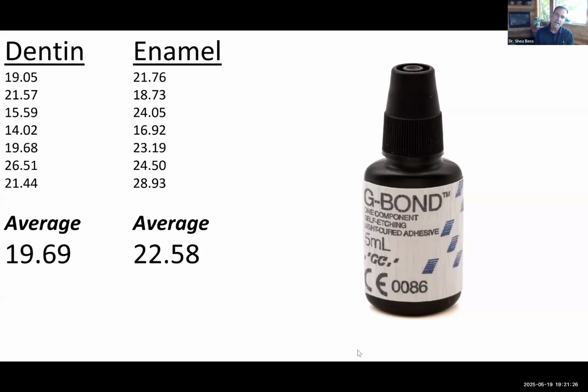And if you remember the other adhesives that we've talked about so far and compare those numbers, G-Bond has a bond strength that is significantly lower in dentin. The other thing I want you to notice with G-Bond is that their bond strengths to enamel are higher than their bond strengths to dentin, which is highly unusual.